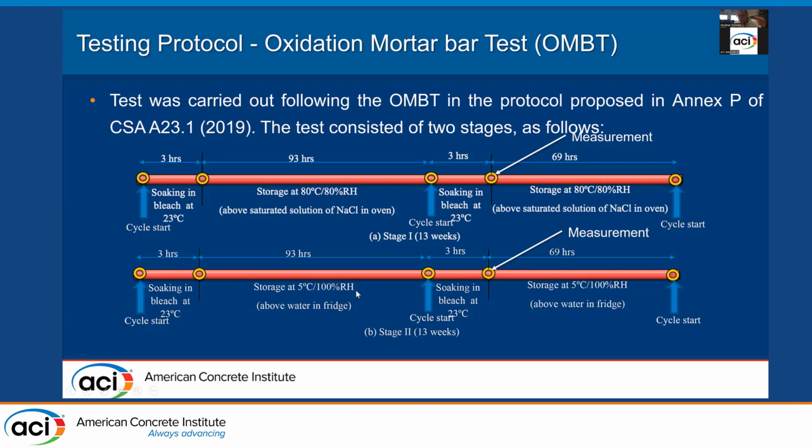This condition is to promote sulfate attack, namely thaumasite, simply because when my colleagues at Laval tested aggregate on site, they found the sulfate attack product was mainly in the form of thaumasite, or solid solution of thaumasite and ettringite. So that's the test in a nutshell: 2 cycles per week, the first 13 weeks for oxidation, and the last 13 weeks for sulfate attack.